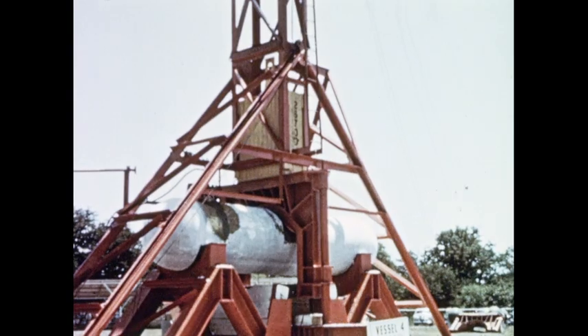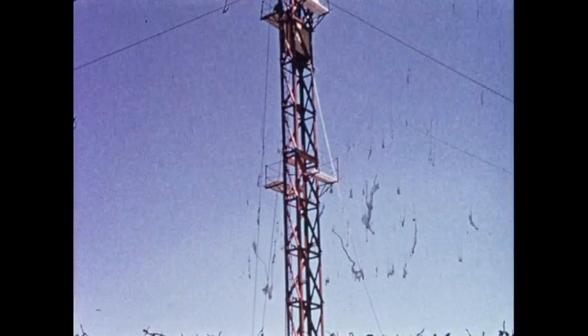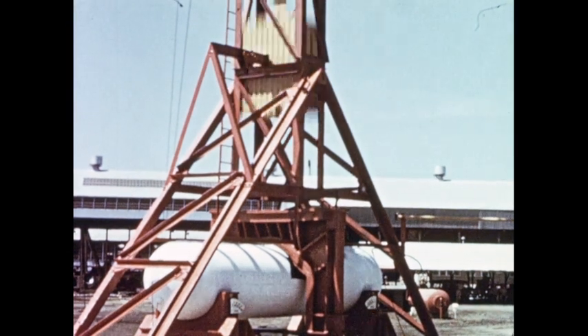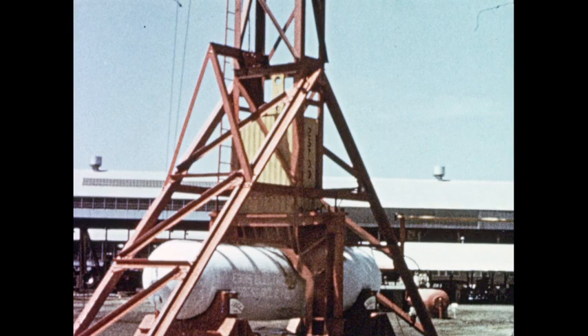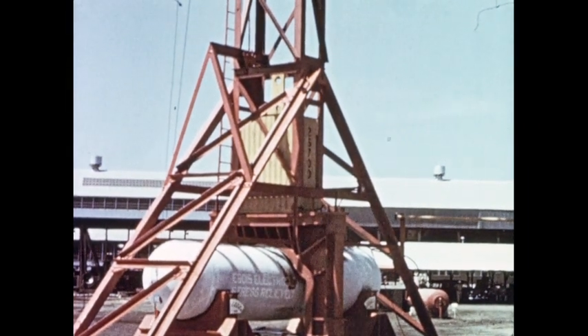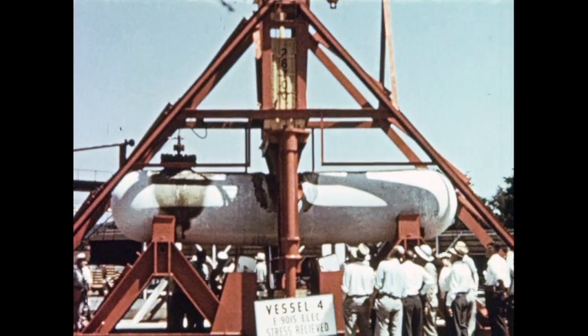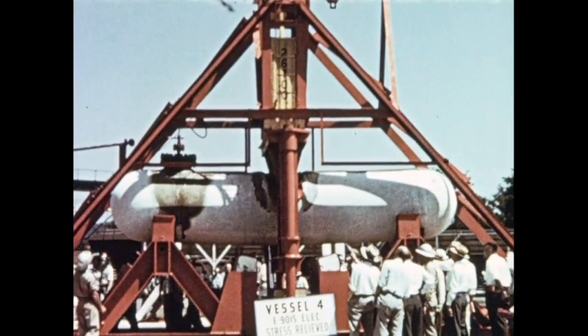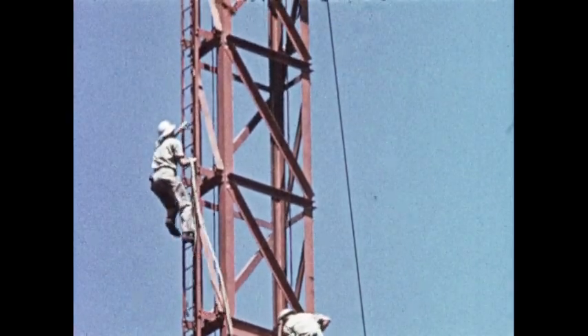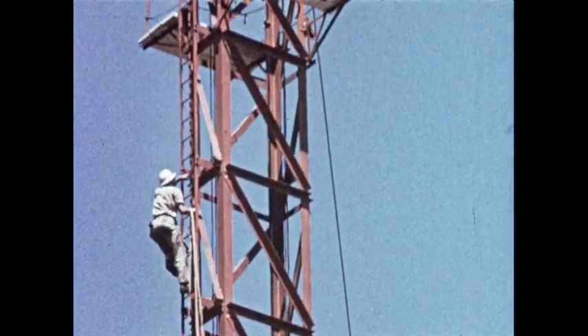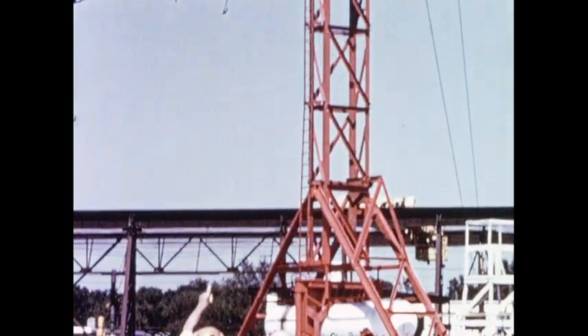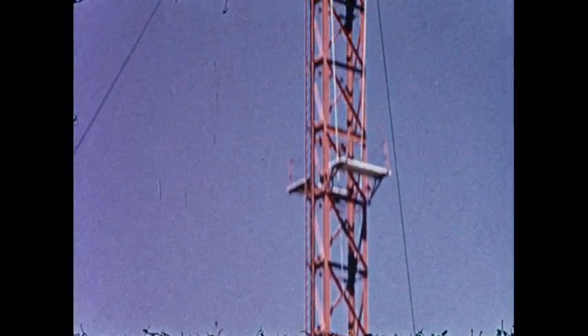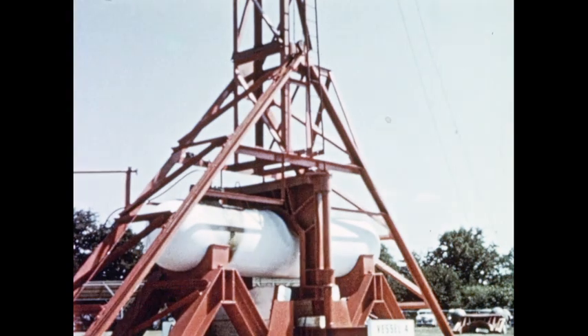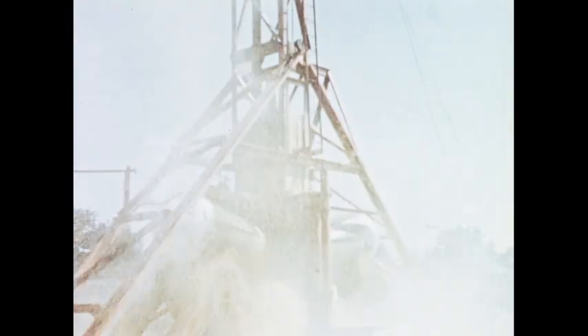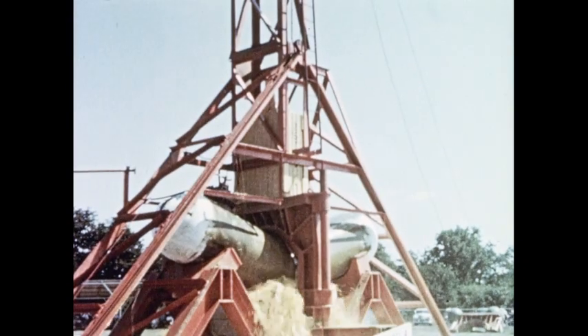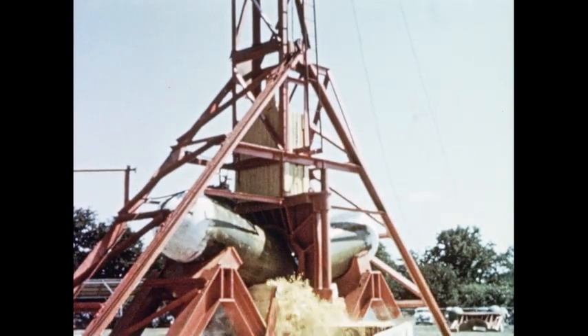Yet below the saddle there was no more than a slight dent. For its second drop, the top rose to 73 feet. A shattering impact of almost 2 million foot-pounds, and there wasn't even a leak. The distortion increased, but T1 still held. For the third drop, the top was raised to over 100 feet above the vessel. T1 had already proved its superiority. This was to be the crusher. It took almost 3 million foot-pounds to rupture the vessel.